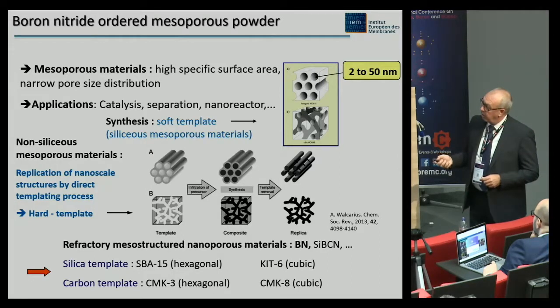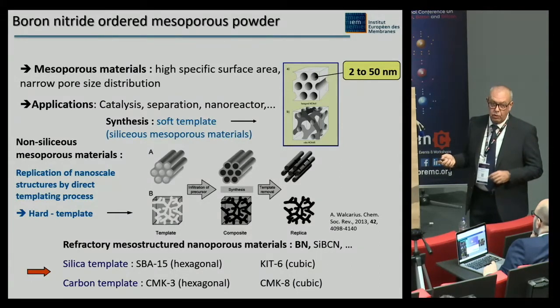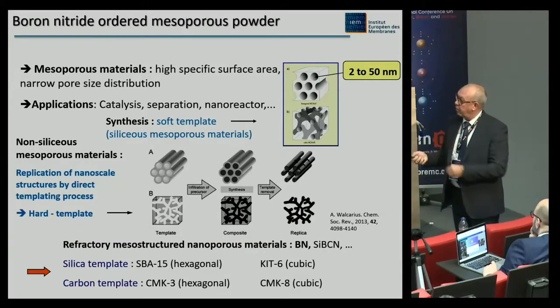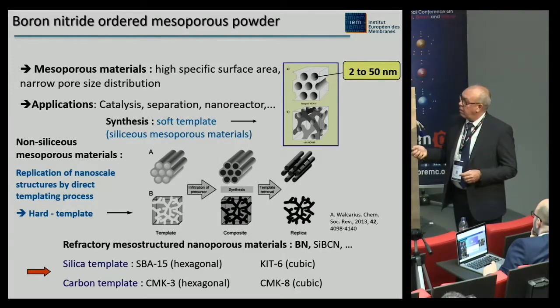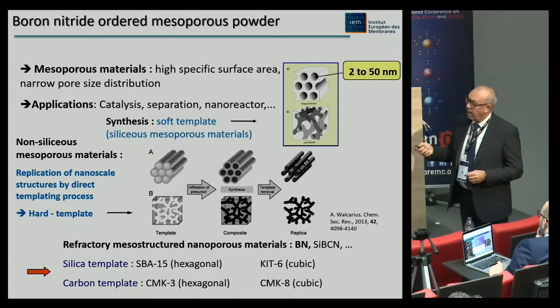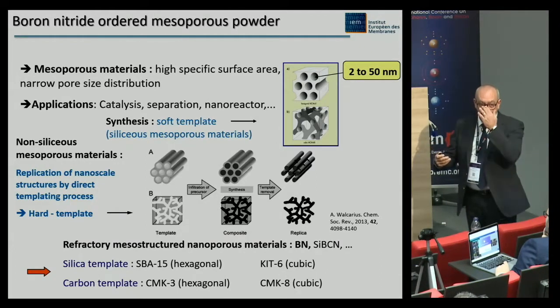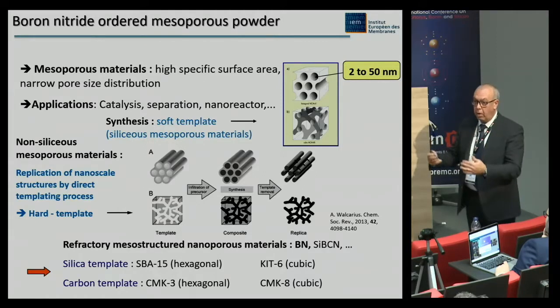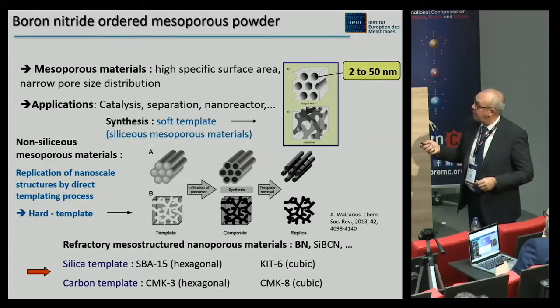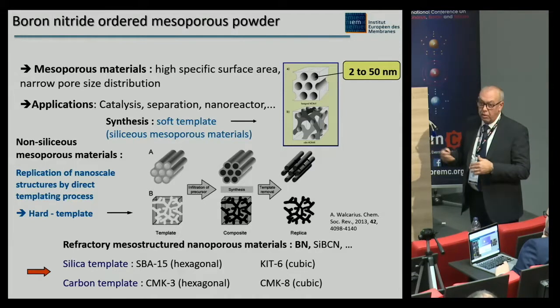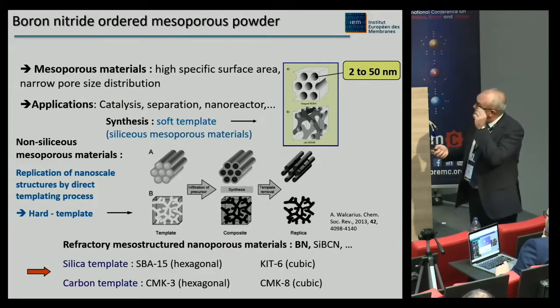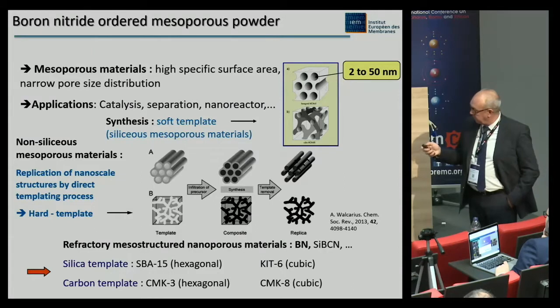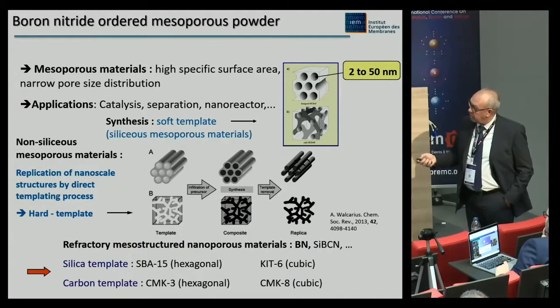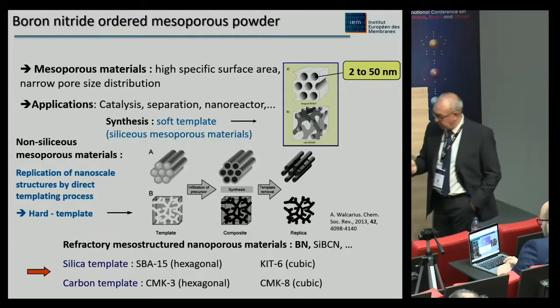And the only method is the hard templating method, which is a long method with several steps. You take a template, you infiltrate the precursor in the template. After that, you convert your precursor into polymer or into a ceramic. And at the end, you have to remove the template to obtain the replica of the starting structure, which is a very long process. Anyway, we've done that for BN and other systems, starting from, for example, silica template SBA15 or carbon template CMK3.